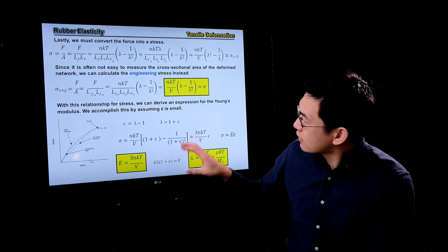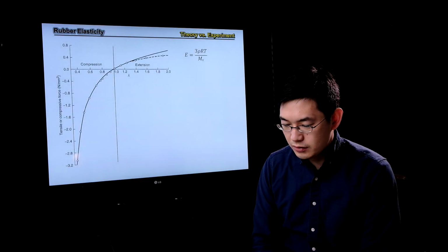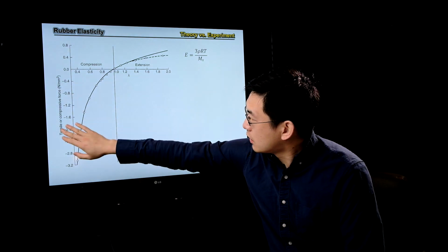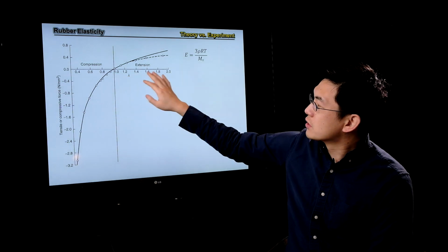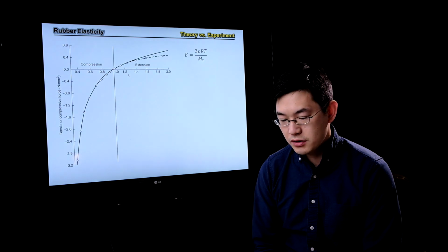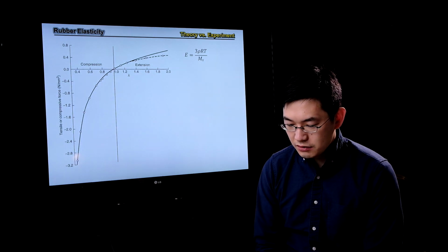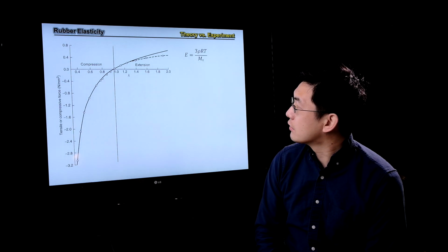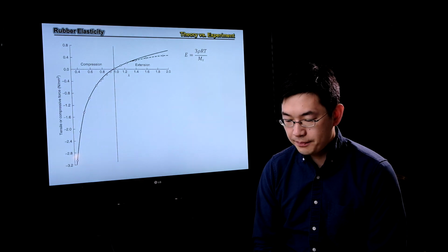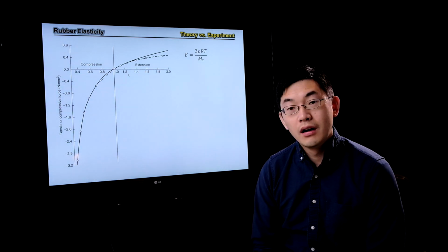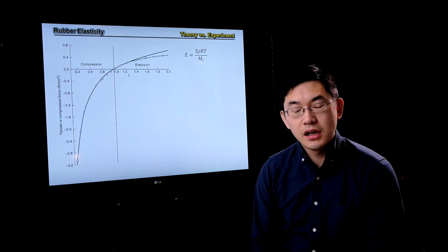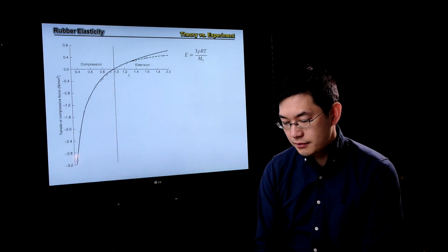Based on the theory we had, people were able to do an example test where you take a rubber and plot tensile or compression force with respect to compression or extension, to see the mechanical response of the material. The theoretical curve is the solid line, while the dashed line linking the dots is the measured data, and you can tell there is pretty good agreement between your theory and your data.